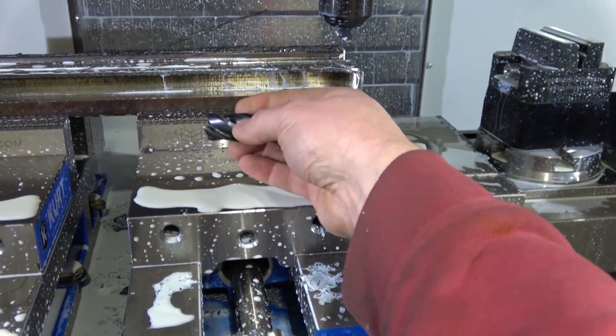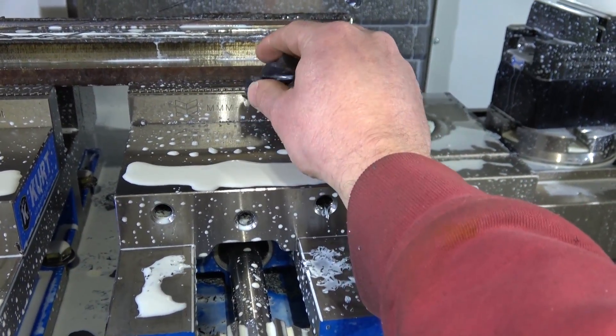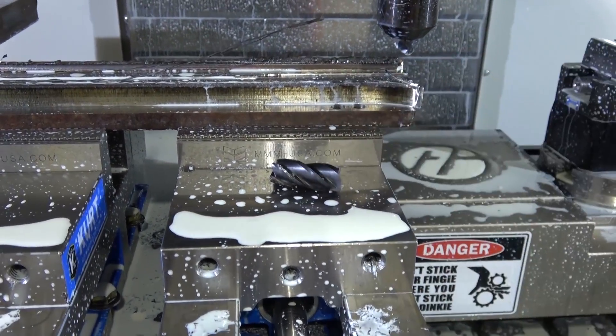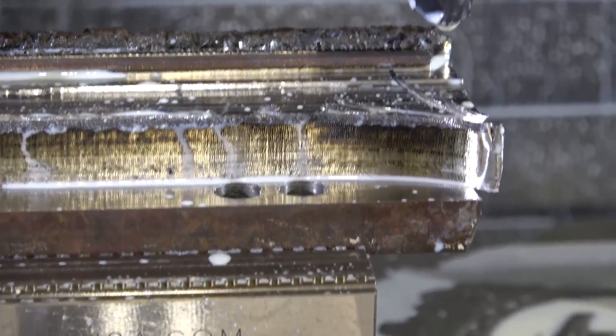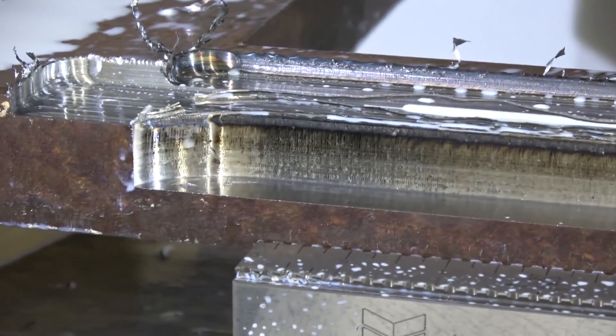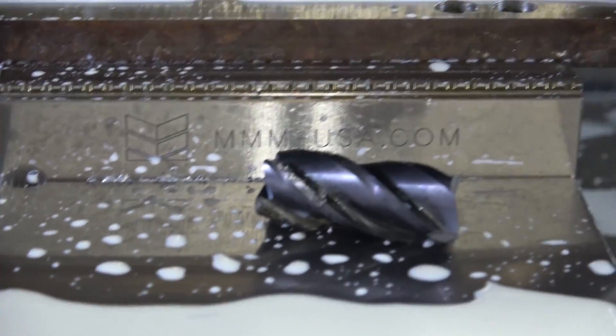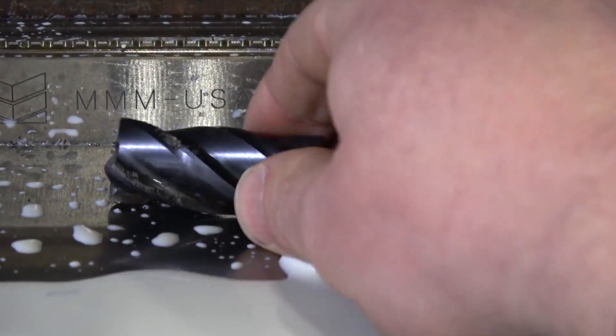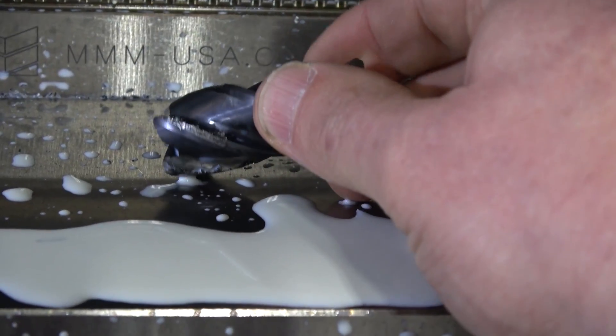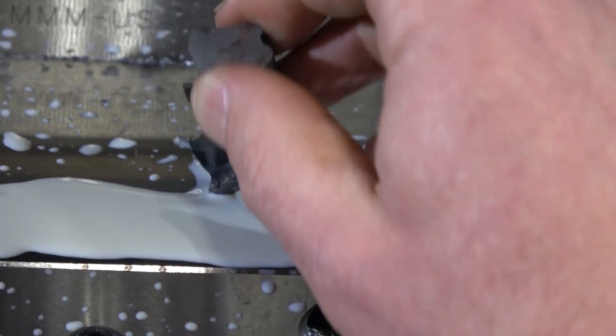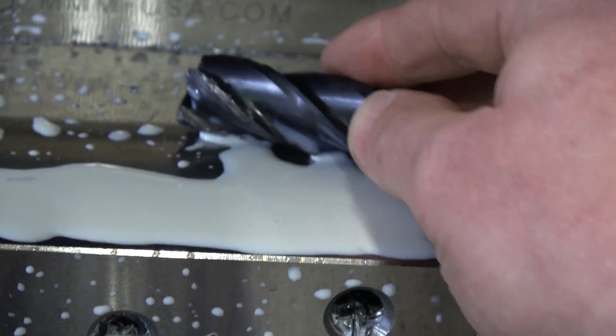That is a fantastic result. If you're in a situation where you gotta run what you brung, you can get it on with just a shitty old end mill. Now, see, surface finish ain't that great. There's some blueing there at the top. That means it got hot enough to re-hardenify. We can see we wiped off. Obviously, the geometry is not optimized for hard milling. It's just an off-the-shelf four fluter. And we wiped the flutes off there, and then we saw the results. So maybe back it back down from 50 down to 40. You got a fair bit of material out of that.